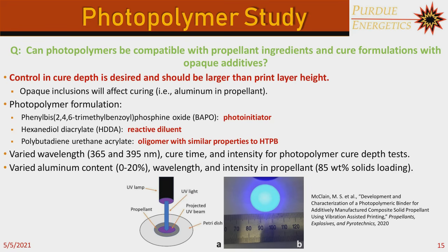Slide 15. So now we've demonstrated that VAP does not negatively affect our combustion performance. But as we showed before, HTPB takes a long time to cure, so our parts will deform if we wait for them to thermally cross-link. So it's important to develop a photopolymer that maybe has similar properties to HTPB, that we can 3D print, that can cure relatively quickly, and that can handle opaque additives, because in solid propellants, it's very common to include opaque additives like iron oxide or aluminum. If you have those additives, that could limit how much your photopolymer will cure.